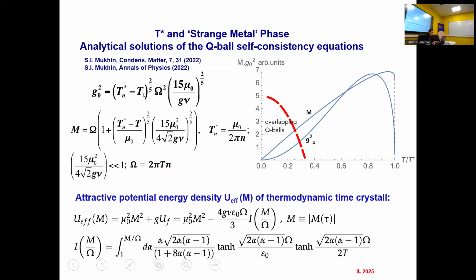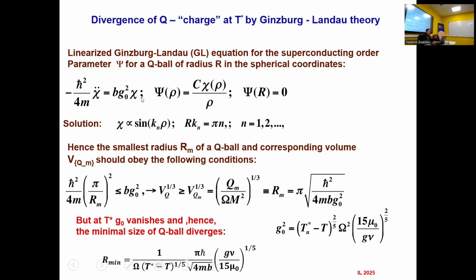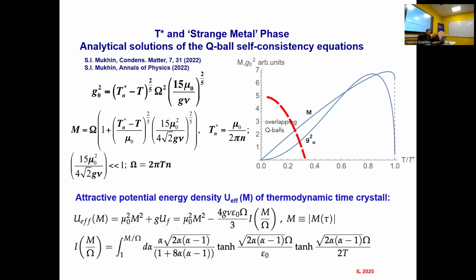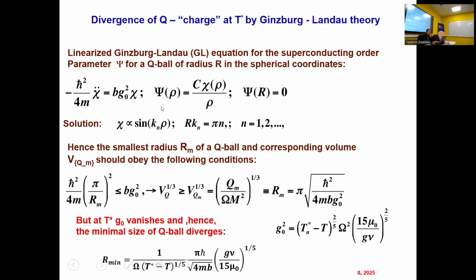G sub 0 squared goes to 0. And it means, this is actually your question about the temperature dependence of all parameters, of the radius of the Q-ball, of M and everything. We know from the Ginzburg-Landau equation, just the usual one, so consider the usual Ginzburg-Landau inside the Q-ball for the superconducting Cooper pair condensate. Close to this zero of the gap, we can linearize the Ginzburg-Landau equation in this way, and rho is the distance from the center of the Q-ball to its volume, inside its volume. And then you have this Ginzburg-Landau equation with B, just some parameter of Ginzburg-Landau which stands in the Ginzburg-Landau functional.